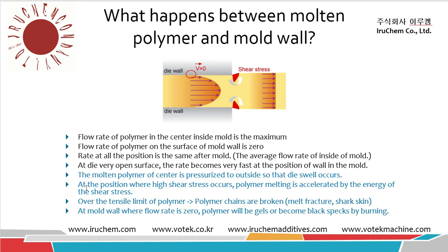So because of this, there is big shear stress. The polymer melt is accelerated at this position, and the tensile stress — because of the speed change — is quite large. So the molecules will be broken very easily at this part, and each molecule becomes very small. In the center position, the speed is quite much reduced. Because of this, the flow shifts to the side, becomes pressurized on the outside, and causes swell outside of the extrudate.